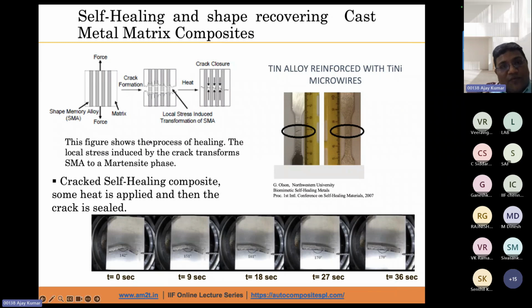So we try to reinforce the shape memory alloys or shape memory materials in the metal matrix, and we see that if any crack develops, can we heal the crack? If not 100%, at least 60 to 80%. If we are able to heal the crack, we can save a lot of lives or accidents. So that is how we conducted a very preliminary experiment where we inserted the shape memory wires, and then we introduced the cracks, and we have seen that this can be healed. So you can see here the defected or cracked sample, and then over the period of time in 36 seconds it has healed a lot. Okay, so this is how we are introducing the self-healing MMCs.